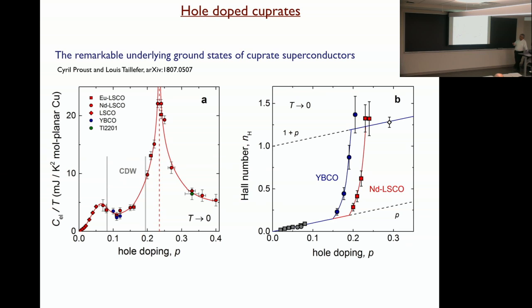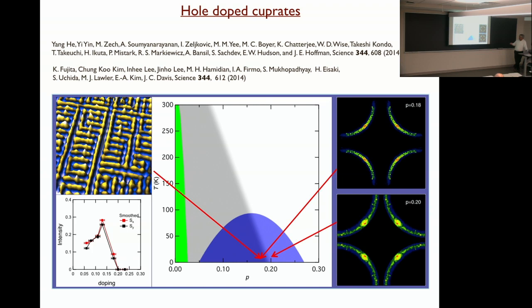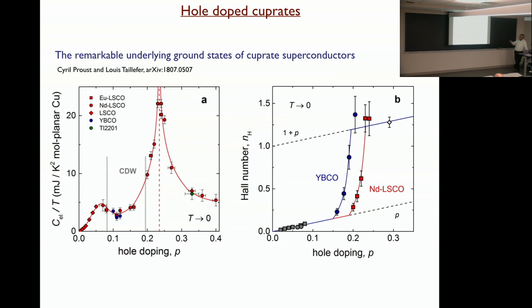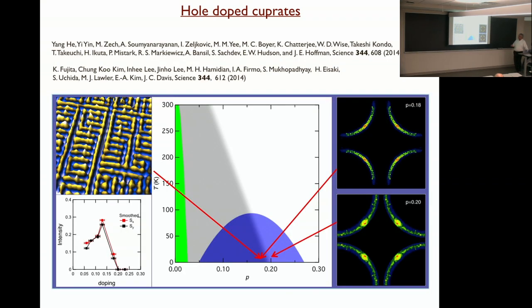If you look at the Hall coefficient again, at higher doping, you see exactly the value expected. If you take this Fermi surface, take the area, work out the Hall coefficient, that's the value. On the other hand, around 20% doping, there's a quite sharp drop in the Hall coefficient. Now, one explanation for all of this could be that there's some broken symmetry. In the doped cuprate, it's clear there's no magnetism. But maybe it's the charge density wave order responsible for what's going on.